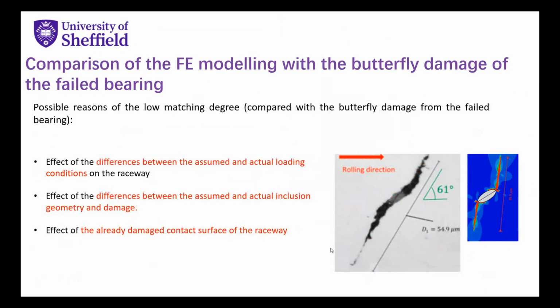First, the effect of the difference between the assumed and the actual loading conditions on the raceway, because we can't simulate the real loading conditions on the bearing, so that may cause the difference. That's the first reason. And the second reason is about the geometry of the inclusions in the modeling. It's just a 2-dimensional modeling, but in the real case, the inclusion is 3-dimensional, and it may have some irregular boundaries, so that is not considered in the modeling.